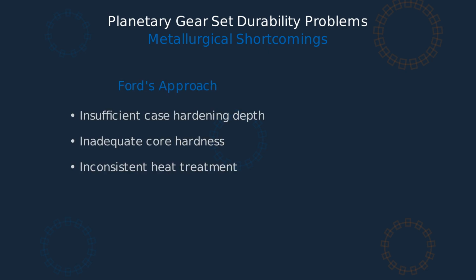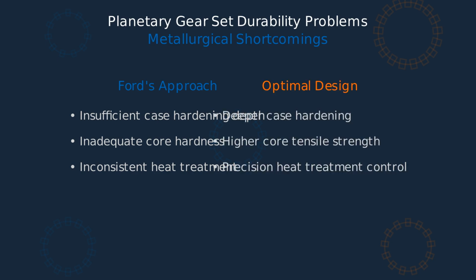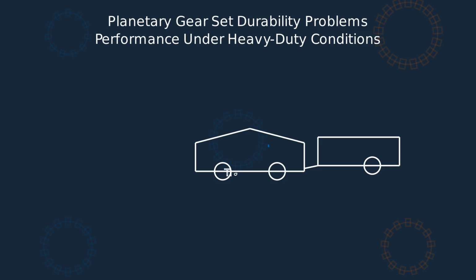The durability issues in the 6R80 planetary gear sets can be traced back to several metallurgical shortcomings. Ford's approach to manufacturing these components has several critical weaknesses. By contrast, an optimal design would incorporate deeper case hardening, higher core tensile strength, and more precise heat treatment control. The planetary gear sets face their greatest challenges under heavy-duty conditions, such as towing. When towing heavy loads, the planetary gears experience significantly higher torque loads and thermal stress.